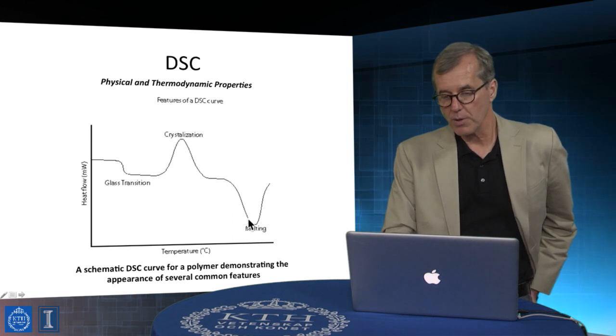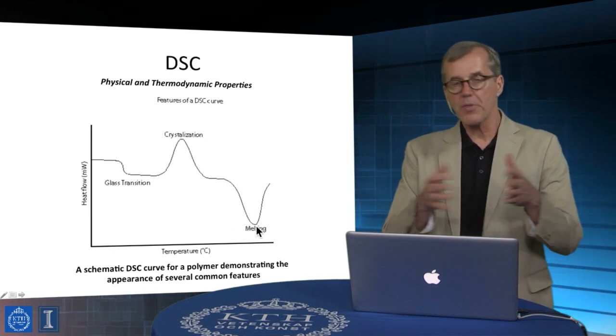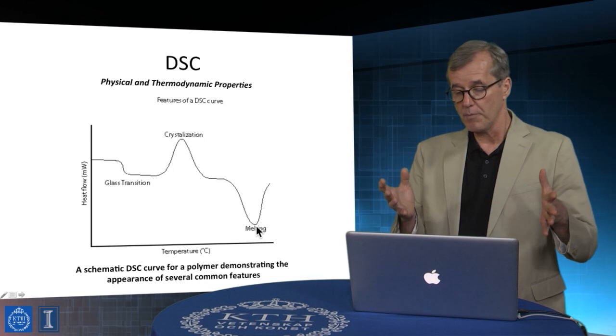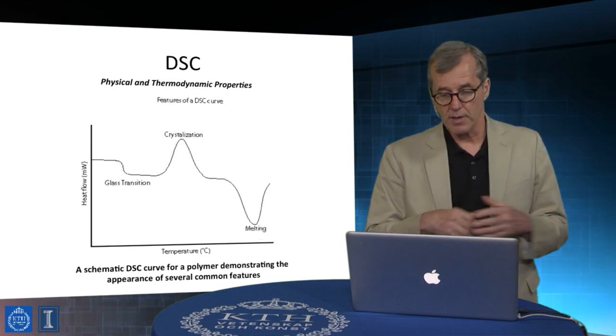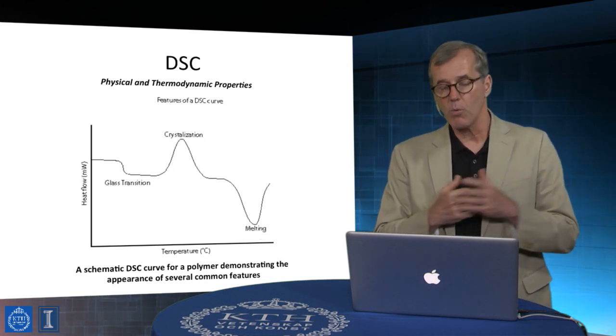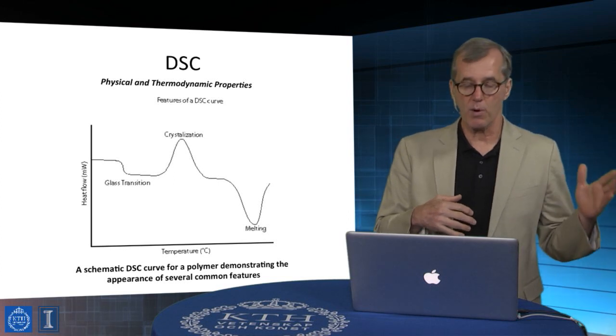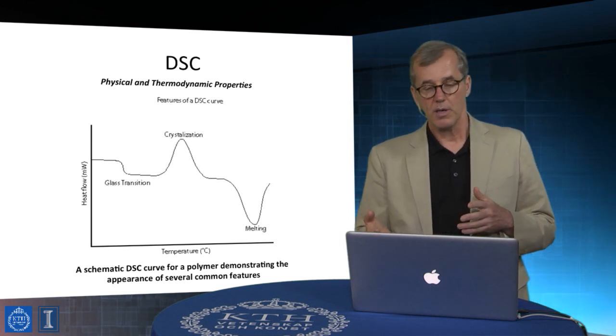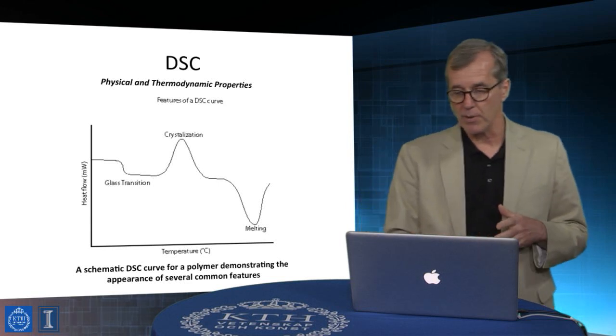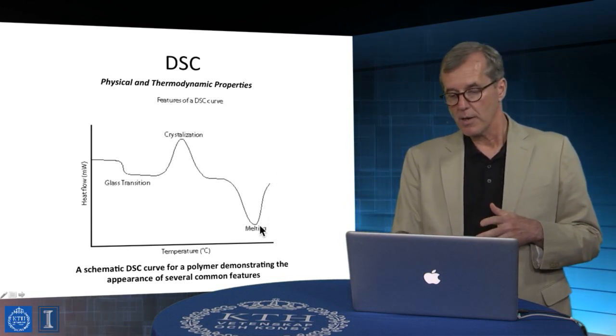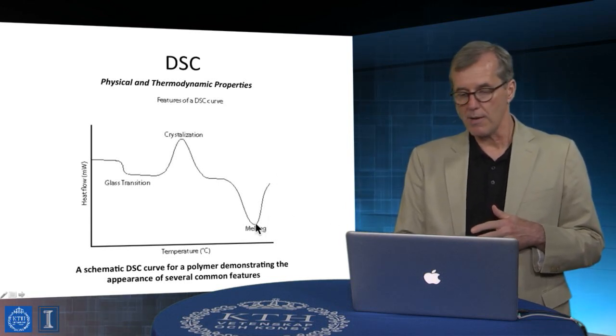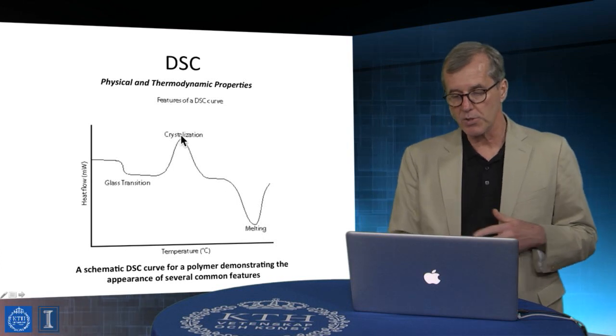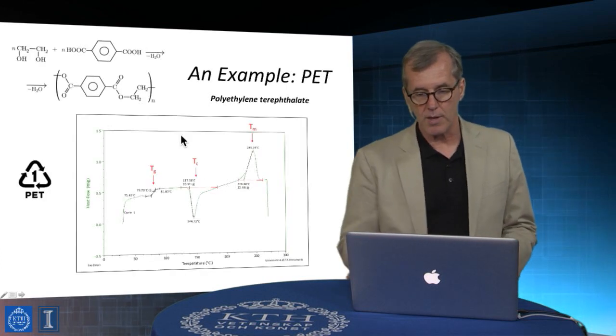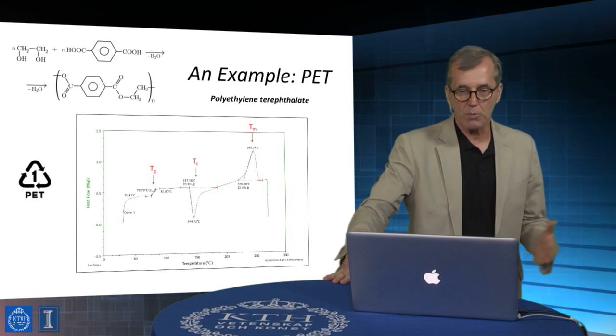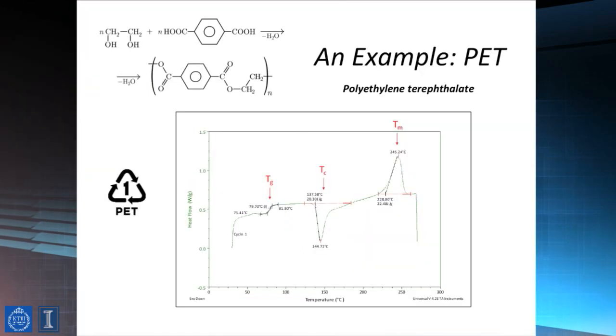And then I get to a place where, in fact, the sample melts. All this can be characterized very quantitatively and actually used to say what in fact was the degree of amorphous and crystalline form present in the sample, for example by comparing that heat flow in the melt state and in these crystallization phases in quantitative form. That's actually a real example of data taken from a sample of polyethylene terephthalate.